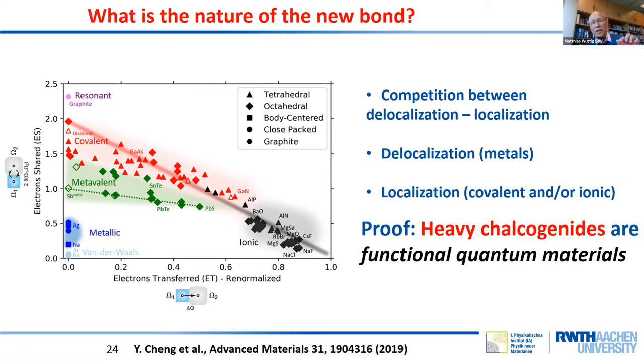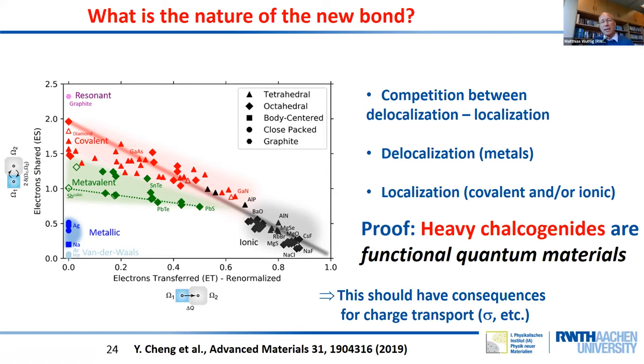And the nice thing is, we can play with this competition. We can either favor localization, going into this ionic direction, going here, or we can favor delocalization going here. We can also have a stress delocalization just going down. So this all should have consequences for the charge transport. So if this map has any predictive power, it should be telling us that by moving in certain directions in this map, we should see significant differences in charge transport, and we expect to see emergent transport phenomena.